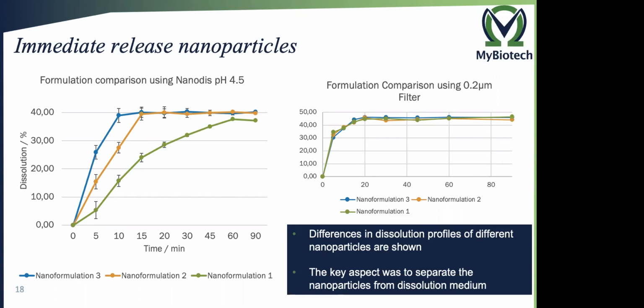But if I do the same dissolution study using a 0.2 micrometer filter, since I also get the dispersed particles within my sample, you will see that there are no differences in dissolution profiles between these three formulations on the right side. So why do I show you this? During your method development, you need a method that allows you to discriminate between different nanoformulations. If you use the conventional filtration through a 0.2 micrometer filter, you don't see any differences in dissolution of these three formulations. They're all the same. But if you can really separate the nanoparticles from the dissolution media, that is when you start seeing the differences between the nanoparticle formulations. And that is what you want to see to be able to say, okay, I go further with nanoformulation 3 that has the highest dissolution rate, and then I will develop a tablet formulation from that.